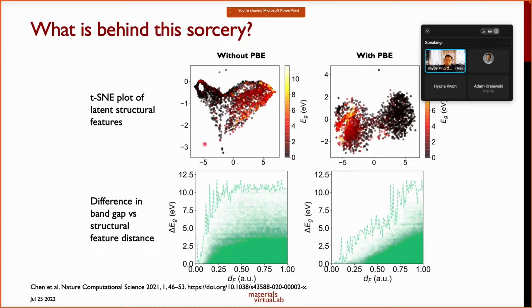So what we found was that when you plot the t-SNE plot of the latent structural features with and without the PBE data, what you find is that with the large PBE data set, you actually have structural features that are much more well-separated with respect to things like the band gap, right? So here you can clearly see all the low band gap materials are on this side and all the high band gap materials are on this side. While without the PBE data, you get much worse separation between the high and low band gap materials. And it is actually this improvement in the latent structural features that we believe is the reason behind the improvement in performance of the multi-fidelity MEGNet on the high value data like the HSE and the experimental band gap predictions. Okay.